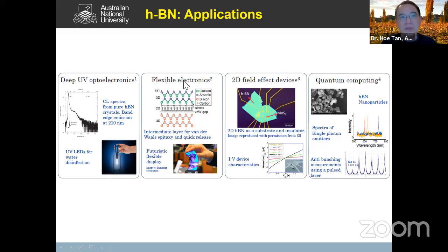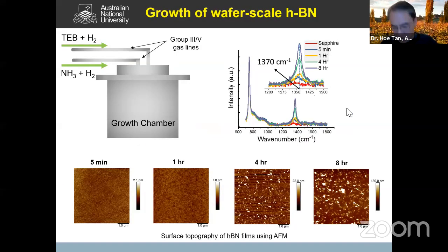Okay. And another thing that a 2D layer can be used for is this so-called van der Waals epitaxy, where we grow the device structure that we want on this 2D material. And because of the van der Waals bonding, we can actually peel this off very easily. And finally, which has only been shown in the last few years, the defects in hexagonal boron nitride give you single photon emission, which is interesting for people working on quantum computing and quantum secure communications.